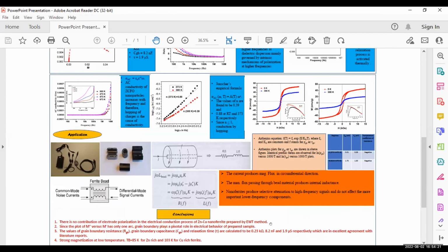And the strong magnetization at low temperature can be seen. The blocking temperature was 85 Kelvin for the zinc ferrite, and 103 Kelvin for the copper ferrite. So these are the three papers that we have published on this dielectric and magnetism. Thank you so much.